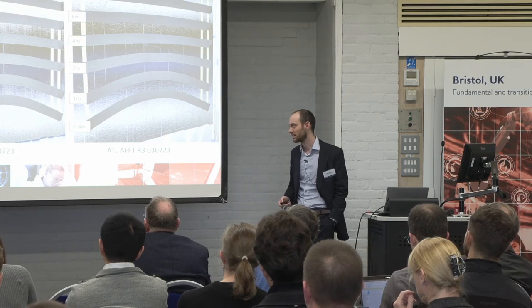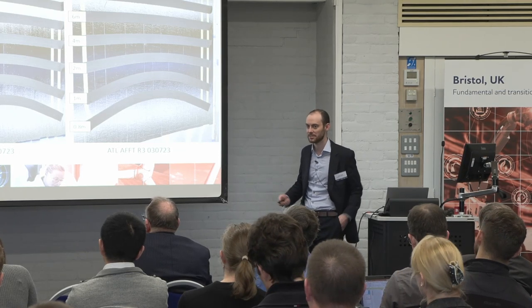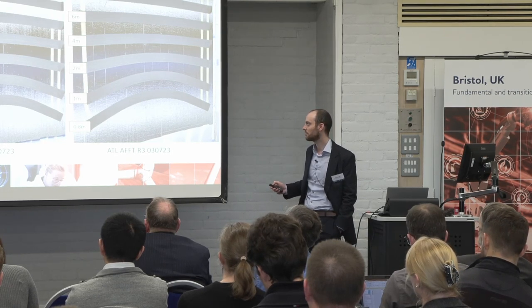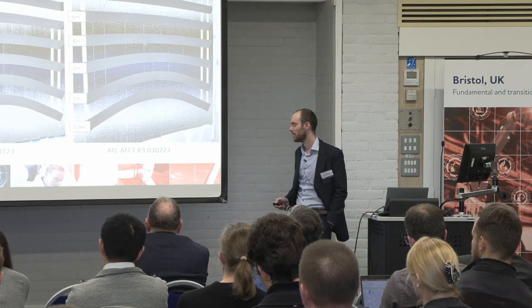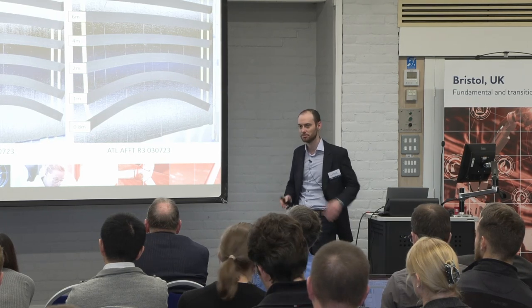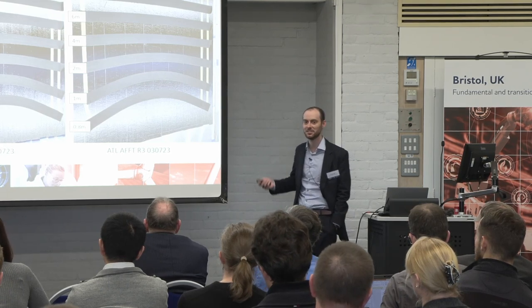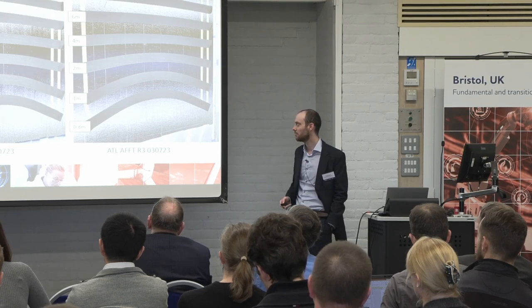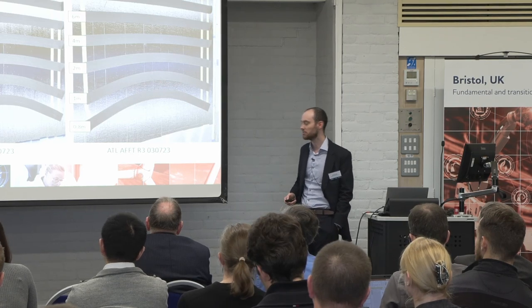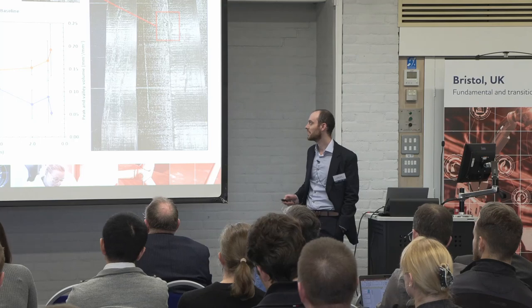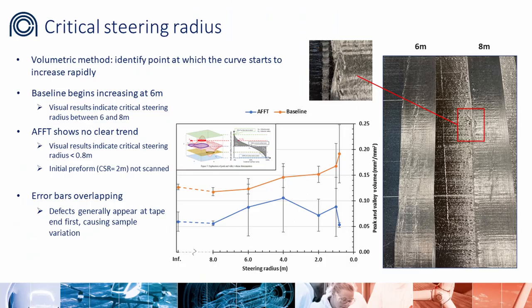Even down to 2 meters, visually, and I'll show the peak and valley volume data just to show we're not hiding anything, it's very good, with no defects, very smooth. In two out of three of the trials, we even got down to 800 mil, which is lower than we would manage for AFP, which uses a much thinner tow. This is a really good result, and I want this picture to stick in your minds as the end result of this project. We are planning to take this further and use this information to design and make, hopefully, a demonstrator component of some kind.